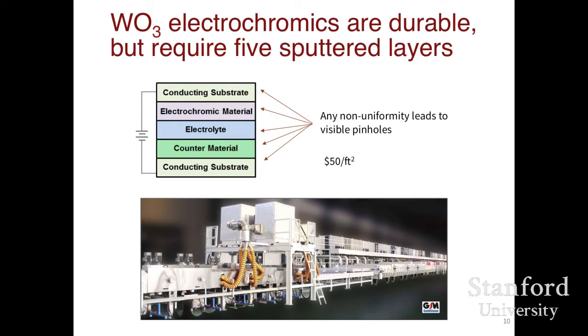Another problem is that sometimes there are pinholes, in other words, regions missing the material, and so those spots don't switch color. And so typically the yield is only about 1/3, and that means that 2/3 of the windows are having to be thrown out. And I think those are the primary reasons why this technology is at about $50 per square foot. And I've heard from people in the industry that $20 to $30 per square foot is probably where the technology would be much more widely adopted than it currently is.